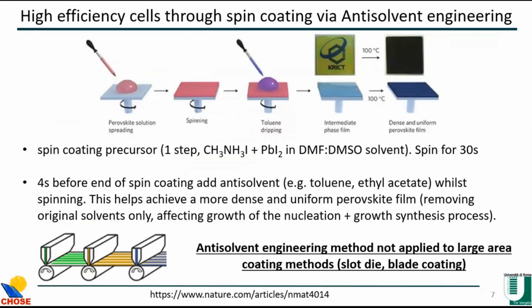So you start the spin coating of the precursor ink, and after about 25 seconds, you add an anti-solvent while it's spinning. The anti-solvent helps move away the original solvents, but doesn't dissolve the precursor materials. And it helps not the nucleation, but the growth of the crystals. So you can achieve better uniformity and larger crystals. However, when you go to roll-to-roll compatible large area techniques, anti-solvent isn't really applicable. So they use drying or heating, and this is gas quenching engineering.